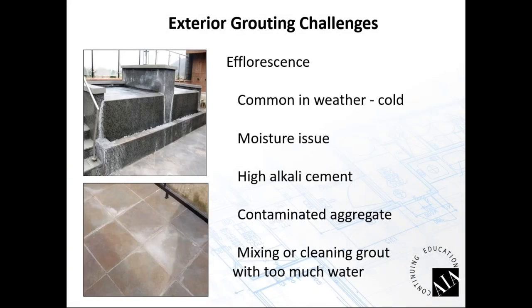Other grouting challenges include efflorescence, which we touched on. It's the white salts that are produced from the free lime that happens as cements cure. That free lime is brought to the surface with moisture. As the moisture evaporates, the salts remain. This is common in cold weather, with moisture coming out of the surface, bringing salts onto the surface. Moisture issues, like rain going into the grout and into the mortar beds, bring the salts to the surface, the moisture evaporates, and the salts remain. And then the different types of cement, the high alkali cement, will leave this efflorescence.